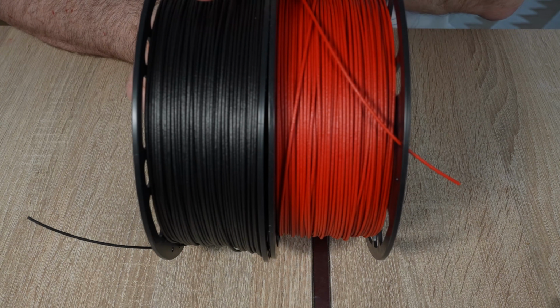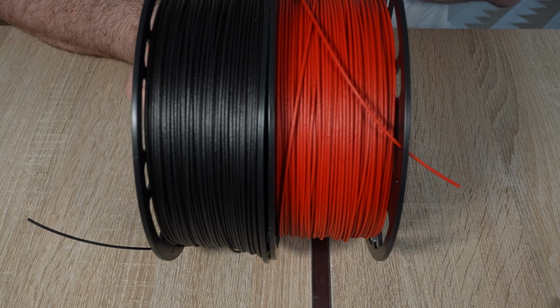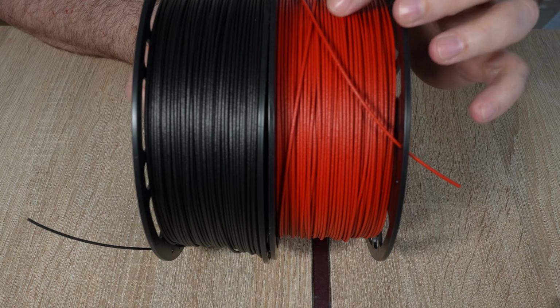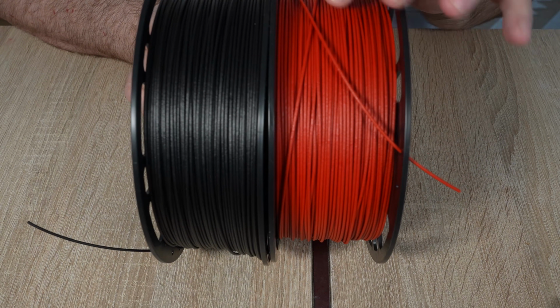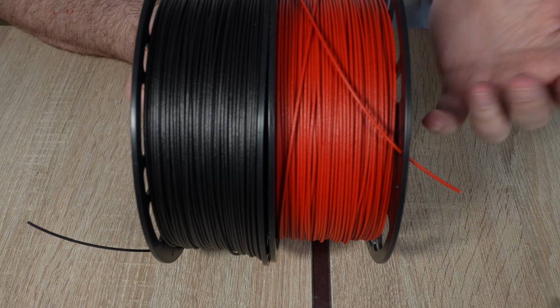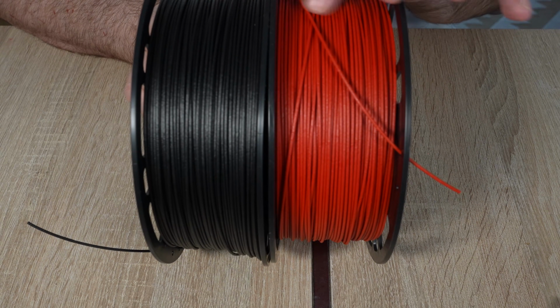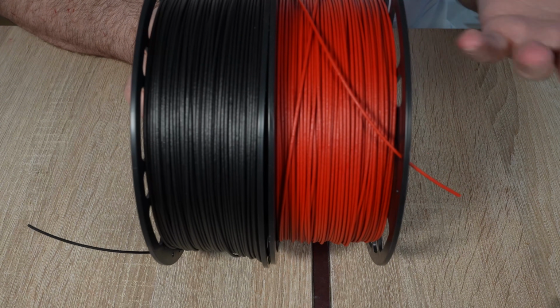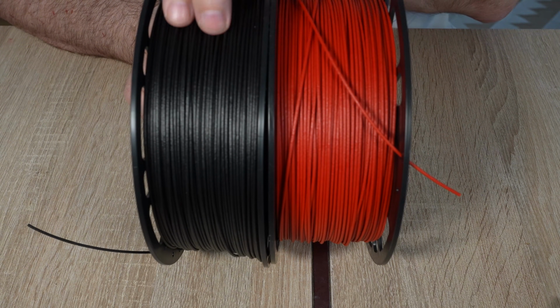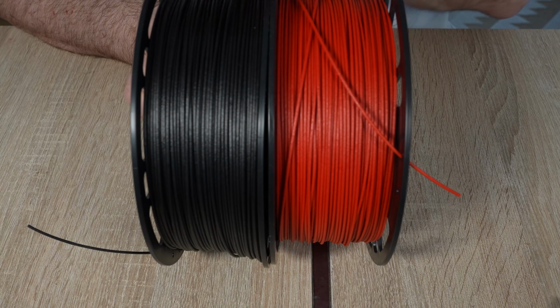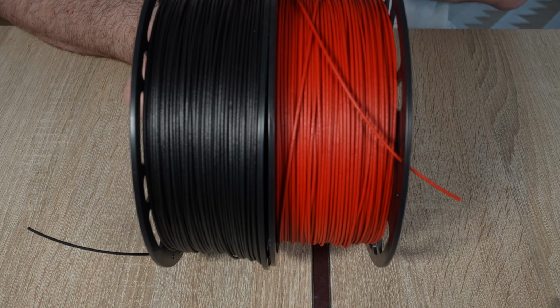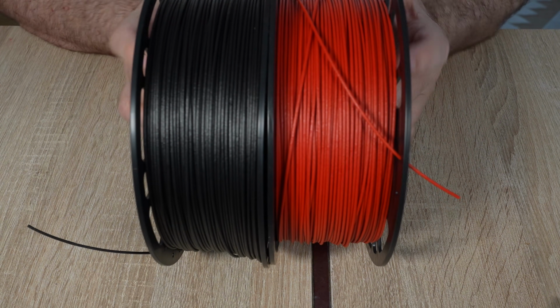Carbon fiber is typically in black color, because carbon fibers are black and usually we have a black or some very dark color. With the glass fibers we have more freedom because they are transparent, and we can have lighter colors too, and this one is in this nice red color. Now I can see more filament here, so maybe the density of the carbon fiber version is lower compared to the glass fiber, because the spool size should be the same. Let's measure them just in case. Theoretically these are both 1 kilogram net weight spools.